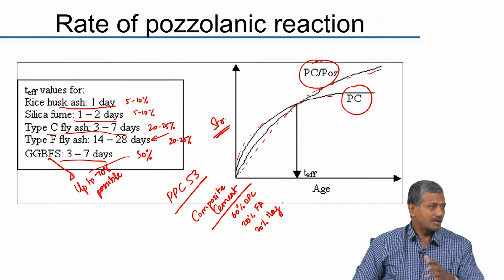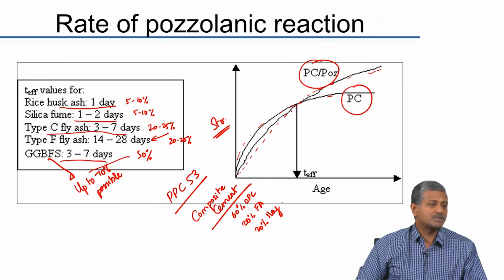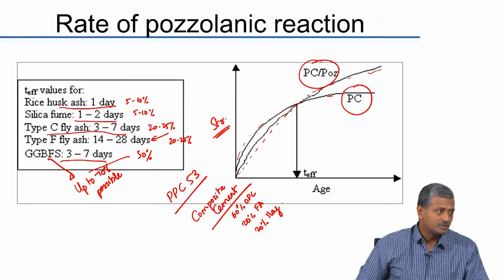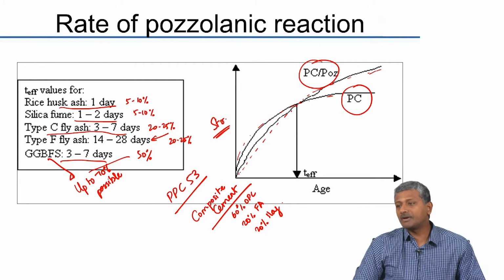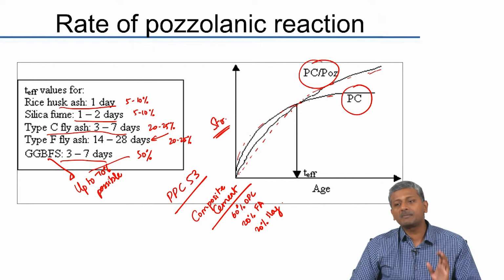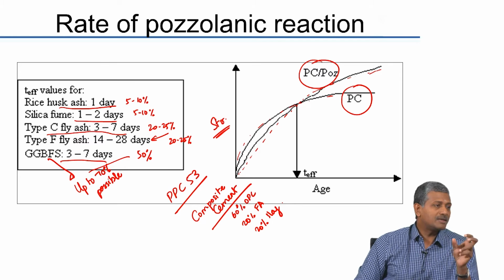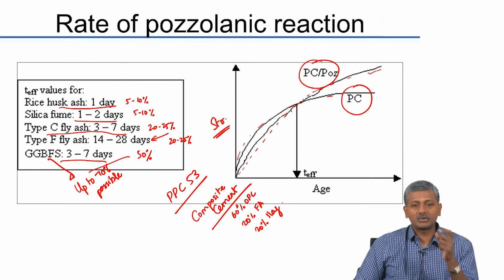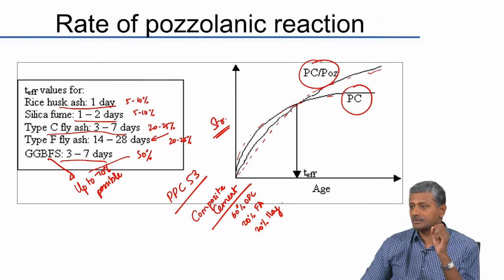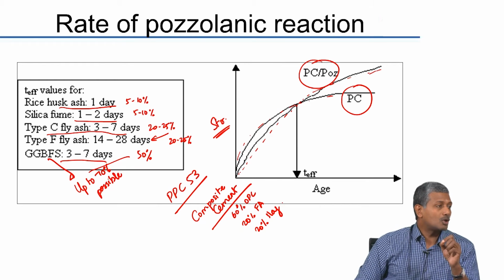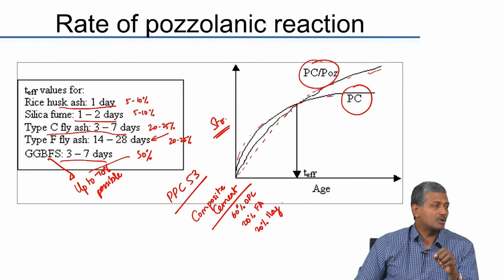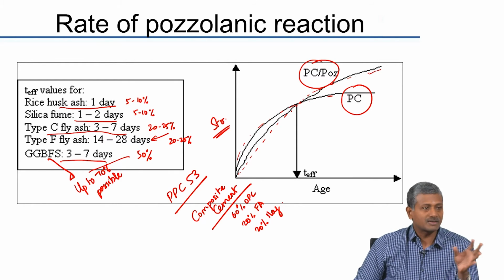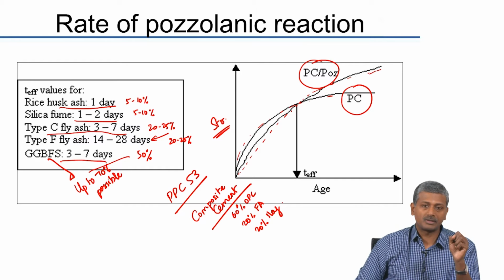Okay. So, there are benefits to be obtained from this. Obviously, your chloride durability will be very good without any doubt. Your heat of hydration also will be lowered, because if you simply replace cement with slag, you do not get that much benefit in your heat of hydration reduction. But in combination with fly ash, you can actually significantly reduce heat of hydration. Okay. Your strength gain will not be severely affected because you only have 20% fly ash. Your slag does not affect strength gain rate tremendously.